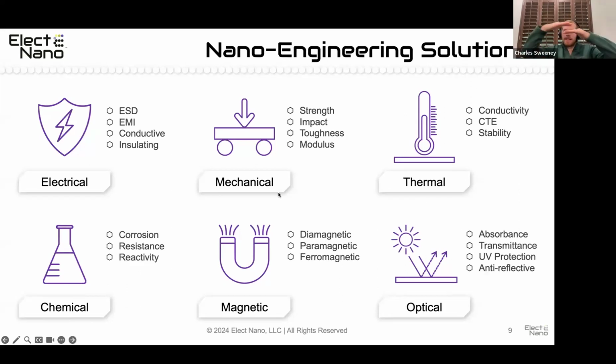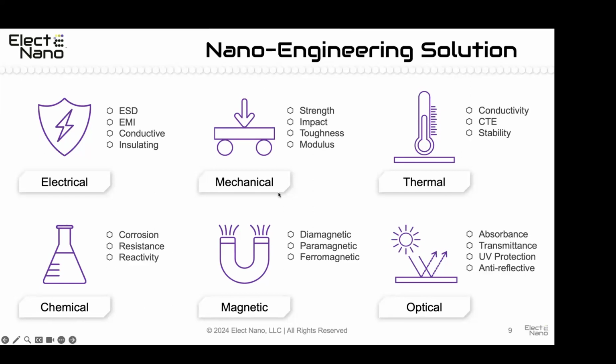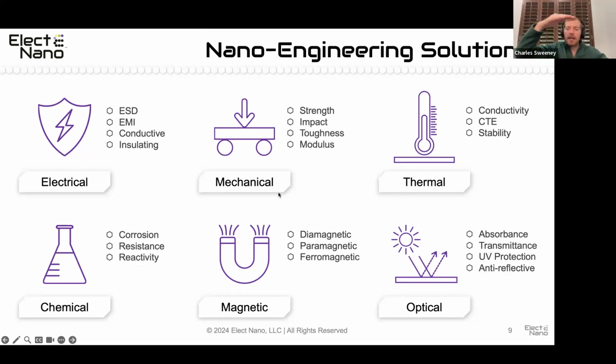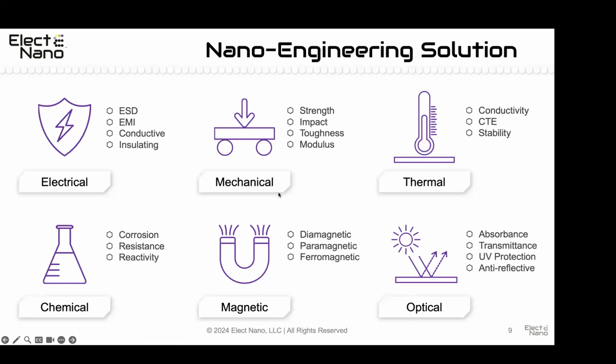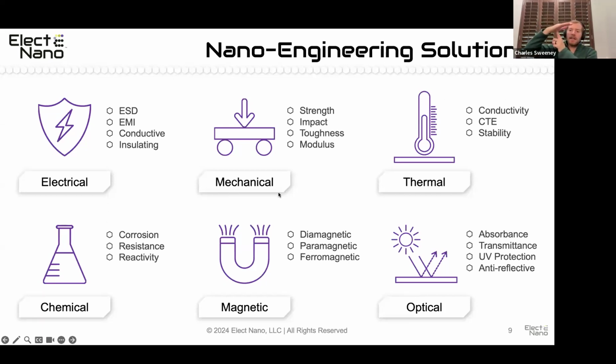So for instance, if you're designing a gap pad absorber that sits against a chip, you may want something that maximizes absorption in a thicker layer, and then a thinner backing where you've increased the nanotube loading in order to maximize the total attenuation coefficient of that layer. So what might happen is if you have an incident electromagnetic signal, it goes through your absorbing layer, and you quench 30 dB of signal. It hits the highly reflecting layer that can be much thinner because it doesn't take as much thickness to achieve that degree of attenuation. The signal actually gets bounced backwards through your absorbing layer, and so you get a doubling of your absorption through an intelligently designed multi-layer system.